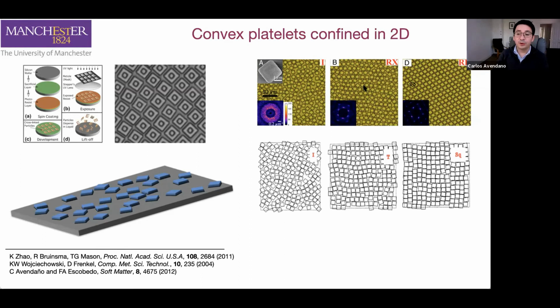And particularly, we have this simulation by Dan Frenkel that he carried out in 2004, where he actually observed the formation of the isotropic phase, but at high densities, he observed the formation of the square phase. And in between, he also observed the formation of something called a tetratic phase. So the tetratic phase is a phase in which each particle has neighbors that arrange in a square fashion, but that arrangement is not propagated in all the space. Locally speaking, they behave like squares, but in long range, there is no order. This makes more sense for this kind of particles.